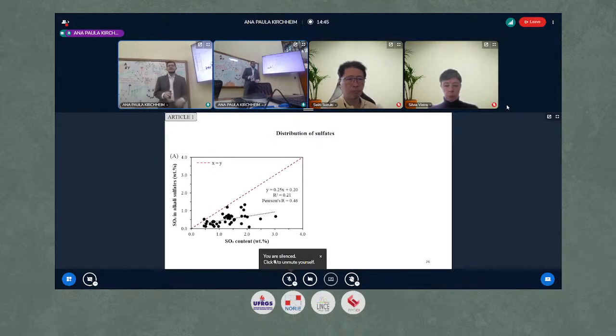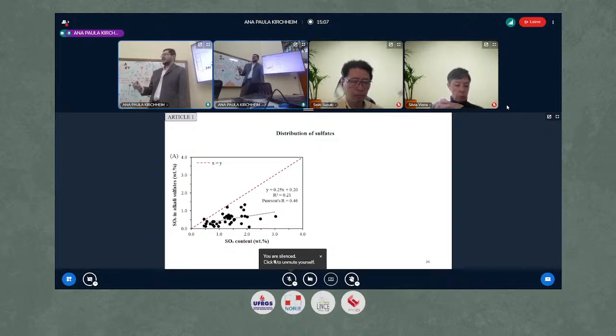Now, regarding the distribution of sulfate, this will be important in the third study. I highlight here that this is the total sulfate content in clinker, while this is the sulfate present in alkali sulfates. We can see that there is a discrepancy, meaning that not all of the sulfate that we have in clinker is present as alkali sulfates.